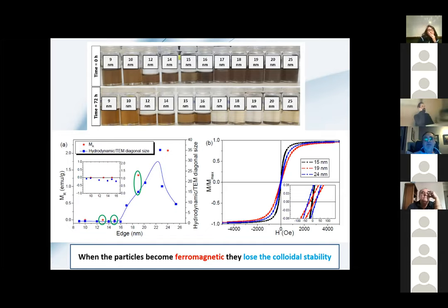To see the origin of this effect, we did DLS measurements, and we see that for the small particles, the hydrodynamic radius divided by the TEM size is equal to one. So the hydrodynamic radius and the size are the same, meaning that they are separated. However, as they become larger, the ratio increases, meaning that at 17 nanometers or larger, they start to aggregate. And as they become larger and larger, they aggregate more and more.